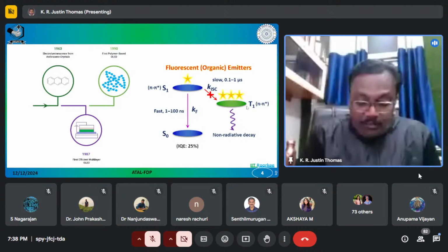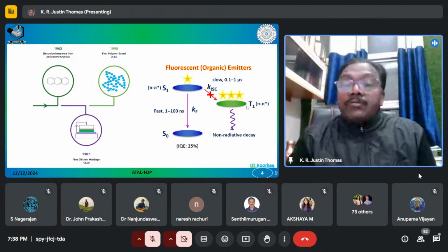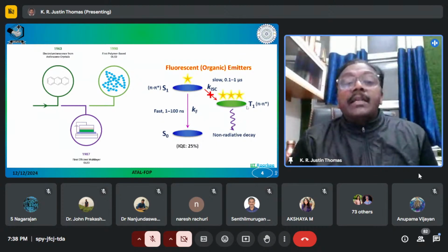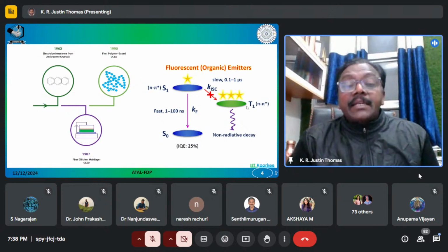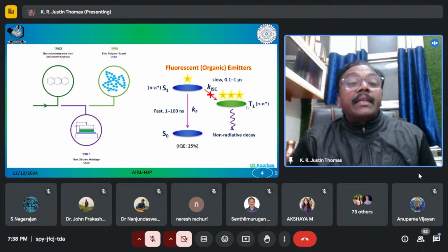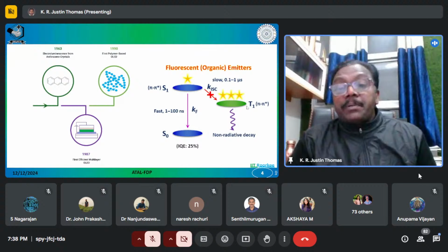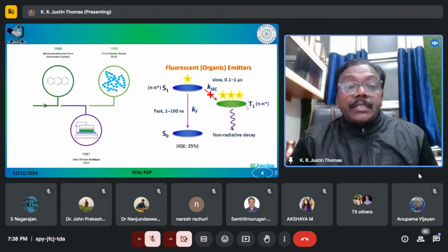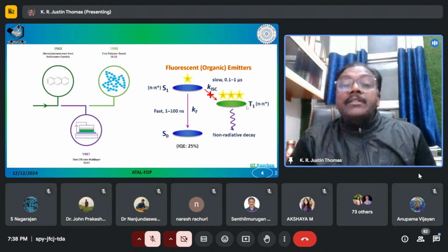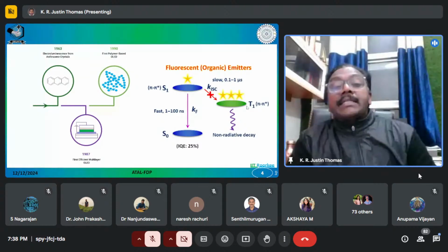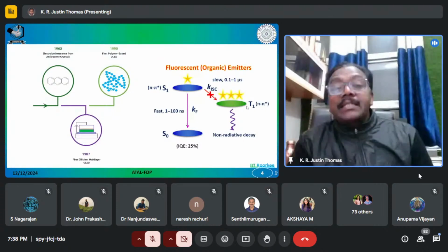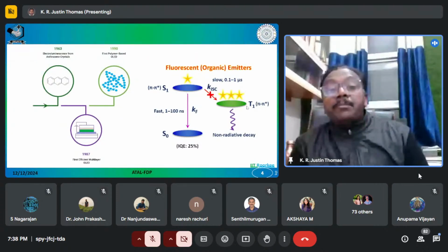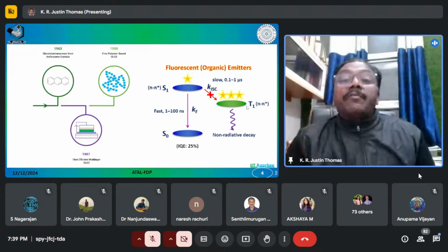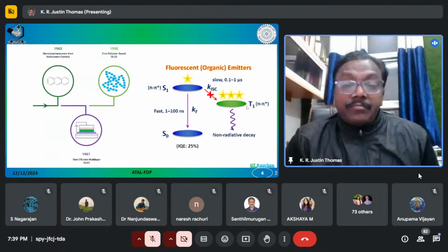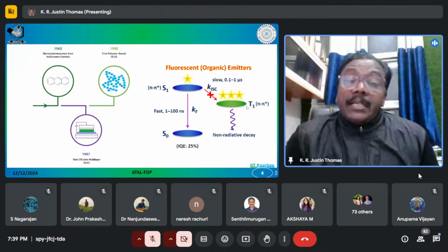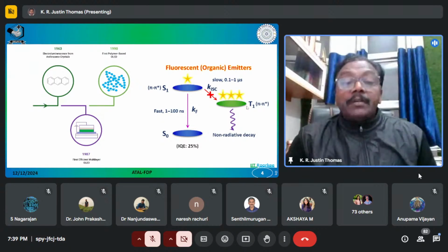So since the fluorescent molecules cannot undergo intersystem crossing, you can harvest only the singlet excitons when you are using a fluorescent organic emitter. So that restricts the internal quantum efficiency of the organic light emitting diodes, which employ fluorescent emitters, to 25%. Then in an organic light emitting diode, there is another factor called outcoupling. And outcoupling efficiency is theoretically 20%. So that means 1/5 of 25%, that is 5%. So 5% is the maximum external quantum efficiency that can be realized from fluorescent organic emitters. But 5% efficiency is not good enough for a practical application.